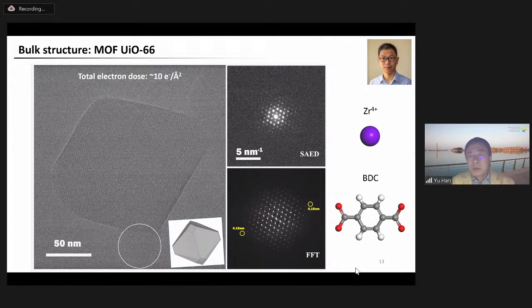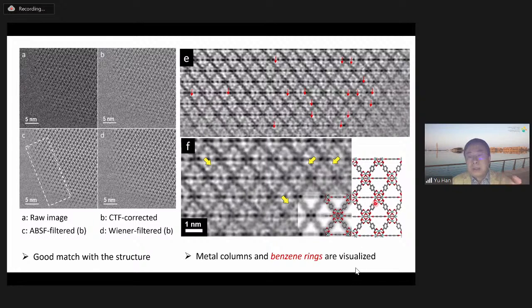So the processed image shows a perfect match with the 110 projected structure model of UiO-66. The important structure features in this projection include the triangular channels, the inverted triangular channels, the zirconium clusters, and the organic linkers. All these structure features can be clearly observed in the image. And in some local places, you can even see the benzene rings in the organic linkers.